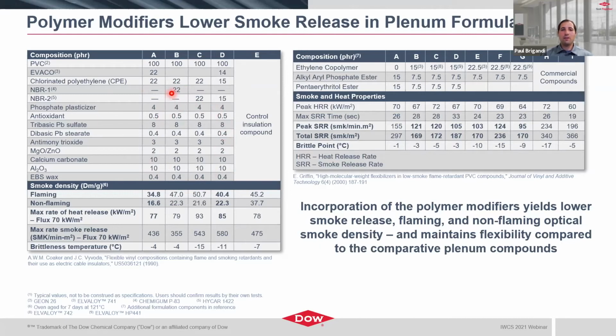But the key point to highlight here is that the systems based on the ethylene copolymer modifier resulted in lower smoke density. That's another key parameter, as we said, for plenum applications: reduction in smoke, so that in the event of an emergency or fire situation, you're able to see leaving the building, as well as, obviously, the different gases that are generated, whether acid gases, et cetera. But here we're looking at smoke density, and those with the ethylene copolymer modifiers are lower than the other materials used. More importantly, it's also lower than a control compound that they used in this study. So it shows the benefit of a lower smoke density, both flaming and non-flaming, as well as lower peak heat release rate, as we showed in the previous slide.